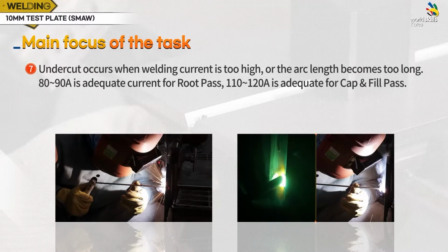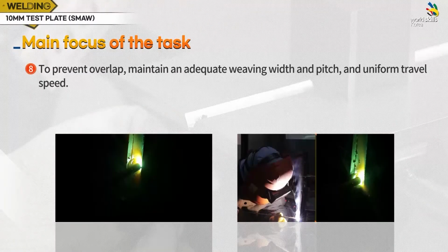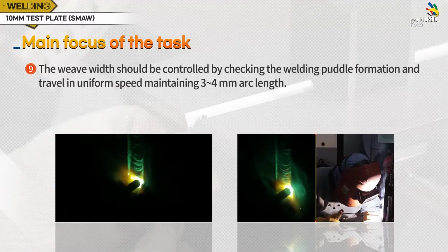Undercut occurs when welding current is too high or the arc length becomes too long. 80 to 90 amps is adequate current for root pass. 110 to 120 amps is adequate for cap and fill pass. To prevent overlap, maintain an adequate weaving width and pitch and uniform travel speed. The weave width should be controlled by checking the welding puddle formation and traveling at uniform speed, maintaining 3 to 4 mm arc length.